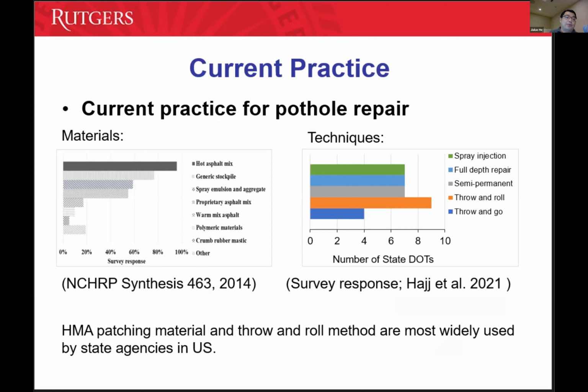So we look at some current practice. The left one is, since this is 2014, what kind of material is used for potholes. Basically, hot mix asphalt is used more commonly because it gives you a relatively longer repair. Spray emulsion aggregate is also one way to do it, but in that case, you rely on a specific machine to do the spray. The proprietary asphalt mix is more like cold mix. In this case, it's more like a combination of modified binder, sometimes even polymer and some cement mixed in, so you can reduce the curing time for quick repair. So basically, different materials have been used.